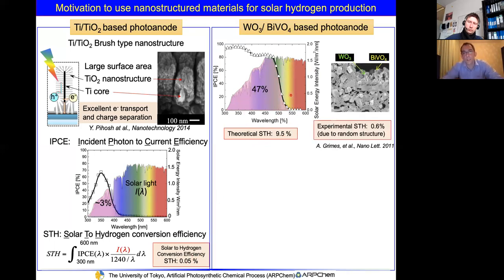I was very motivated by this material when I read a paper published in Nano Letters in 2011. At that time, Grimes experimentally realized a solar-to-hydrogen conversion efficiency of 0.6% on a random structure. What we can see from this SEM image is tungsten oxide nanorods covered by bismuth vanadate material.